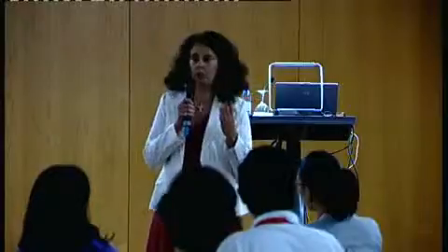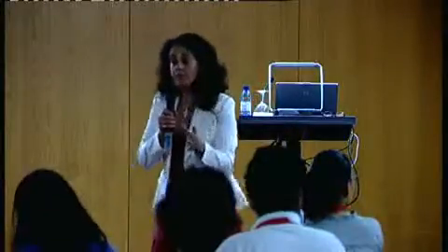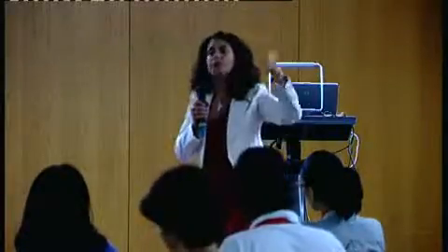Now going to barium titanate. Both of them are prototype perovskite cubic structures, which have some of the best properties. Lead titanate is very difficult to use as a bulk because during the phase transition it exploded, as it has a very high volume change. Barium titanate has been used since the Second World War. It's not the best material, so that's exactly what the Japanese community is doing now. It's improving the properties of barium titanate to substitute PZT.